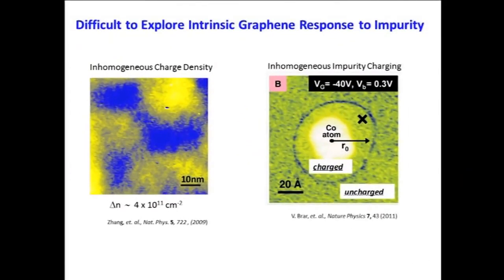And you can see that here by this ring. This is a phenomenon that people have seen in other STM experiments as well. This is what we sometimes refer to as an ionization radius. And what it means is that when the STM tip is outside of this radius, the atom is in one charge state, but when we go inside of the radius, it switches to another charge state. And that's due to the fact that the tip is a movable gate. So these are problems for us.